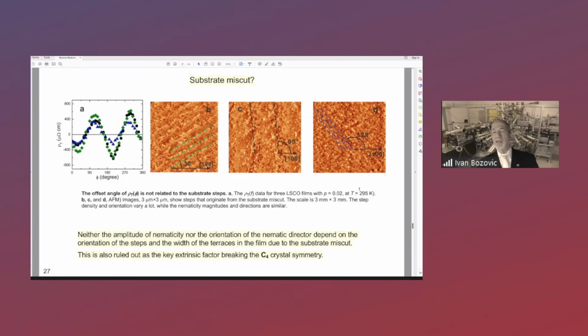But these three substrates have steps at very different spacing and also different orientation. And nevertheless, the amplitude of the nematicity and even the orientation of the director are about the same. That means that these steps do not matter really when it comes to nematicity. And since we know the miscut angle, and we know the in-plane and out-of-plane resistivity, we can calculate what effect we would expect. And indeed, it's like 2 to 3 orders of magnitude smaller than what we experimentally measure. So that's not the explanation either.